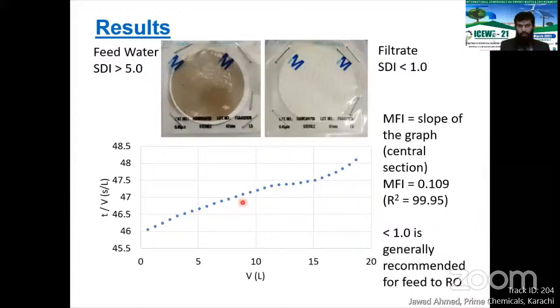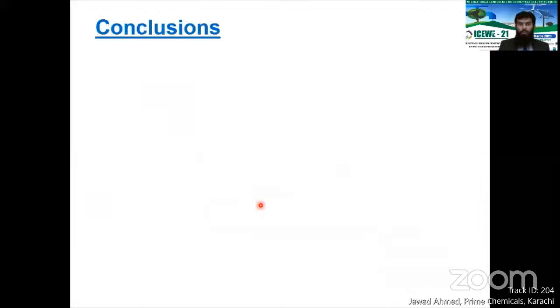The slope of the curve in the central region, which can be shown through the pointer over here, was calculated to be 0.109, with a regression coefficient of 99.95. Again, less than 1 is generally recommended for feed to RO membrane. So our value is 0.1 against a recommended value of less than 1. So it's excellent feed water for the downstream RO membranes. Again, it represents excellent conditioning of the water for feed to RO membrane.